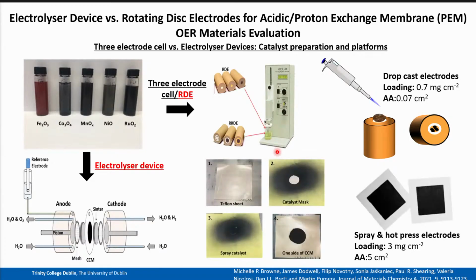But for an electrolyzer device, it's completely different how you make your catalyst electrodes. So essentially, for an electrolyzer device, you will use a Teflon sheet first, and a catalyst mask. You will then spray your catalyst onto your Teflon sheet. And this is essentially one side of your catalyst coated membrane material. So then you do this for one side. So you do this for your anodic side, and also the same for your cathodic side, which is your HER.